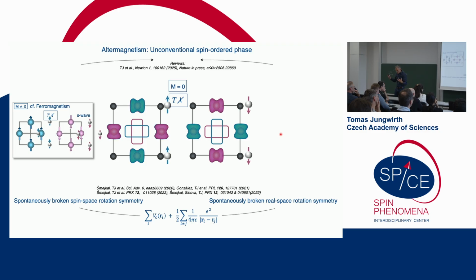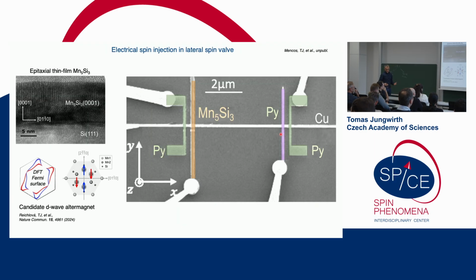And of course, because we break time reversal symmetry in the electronic structure, we also have the property that when we go to the time reversed state of our system, that means when we flip the spins, when we flip the order, the polarization of the electrical current also changes sign. So this is the same as in ferromagnets. These ideas, which were brought forward theoretically, and also the strength of these effects, have been estimated in some altermagnets to be of comparable strength as in conventional ferromagnets.